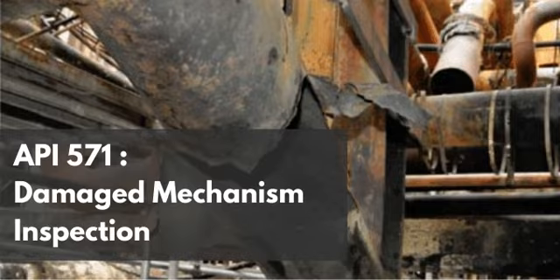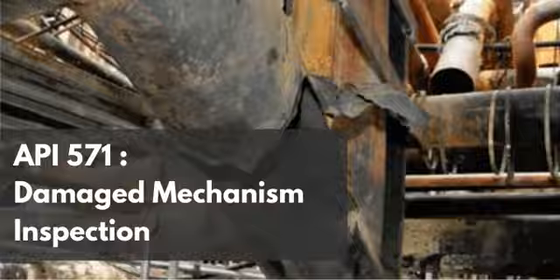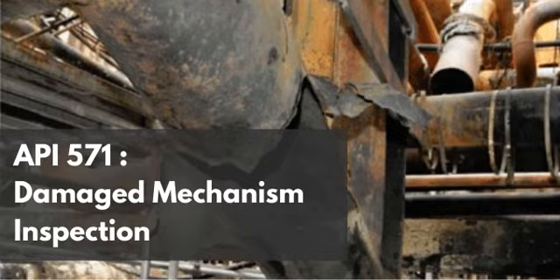Yes. By measuring both the magnetic field component parallel to the crack and the component perpendicular to the crack, complex algorithms within the ACFM software can calculate not just the length of the crack, but also the depth. Exactly. It provides a highly accurate mathematical estimation of the crack's depth. This allows engineers to conduct fracture mechanics assessments to determine if the vessel is safe to operate or if immediate repair is required. That's incredibly powerful data.